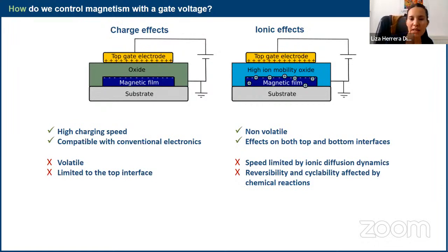We know well that for spintronic systems, we care a lot about the bottom interface with the substrate, because the substrate most of the time is a heavy metal material, which we're going to need to use for SOT or for DMI in particular. So we would also like to bias this interface, and this is not something we can do with charge effects. This is really where ionics comes in. In ionics, we use a similar structure. The only difference is that this oxide is now a high ion mobility oxide, a material where ions can easily diffuse. Here we use an electric field, a gate voltage, not so much to induce charges at the surface of the magnetic film, which will of course happen, but to move ions in the oxide. Once these ions move towards the magnetic film or away from it, they induce large changes in the magnetic properties. And the good thing is that this is non-volatile.